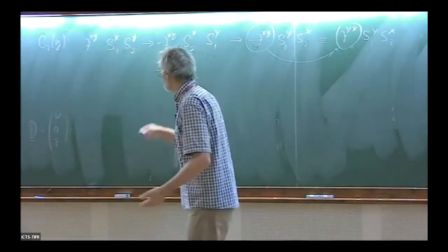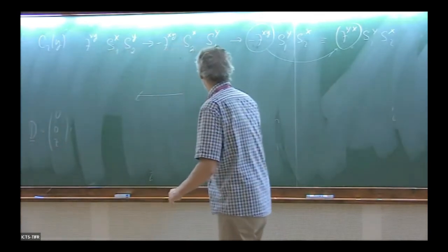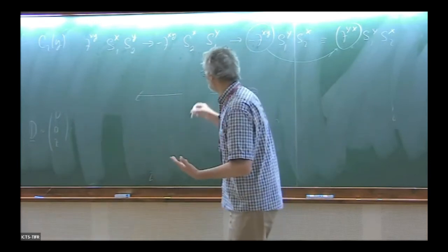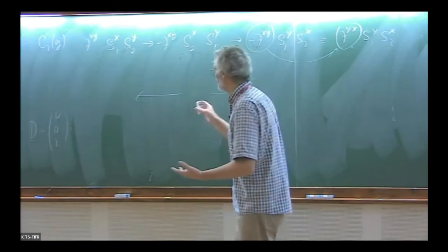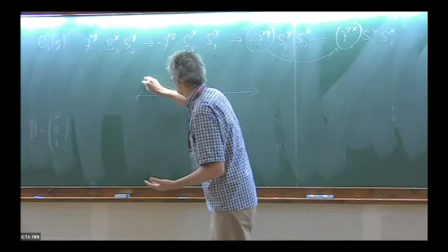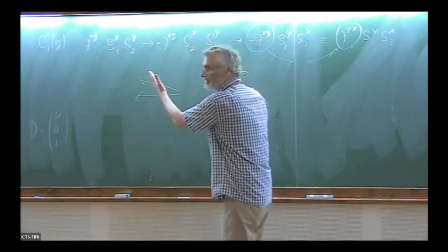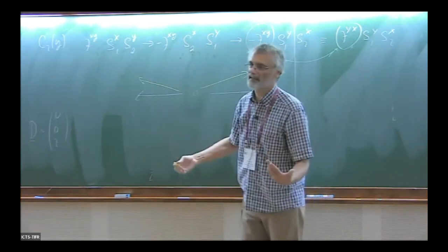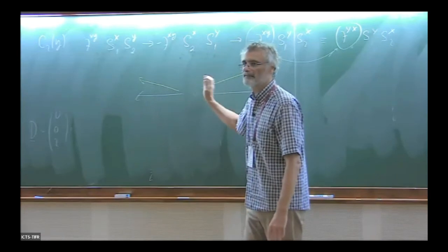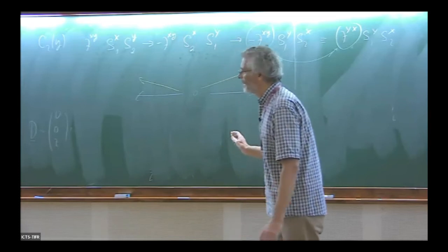So if we have a configuration, this typically arises next to an antiferromagnetic exchange. Antiferromagnetic exchange wants to make the spins antiparallel, and this term would like to have some finite volume. So suppose that the D vector is pointing out. It can gain volume if the spins start to tilt a little bit. If they tilt, then they will reach some compromise between the DM interaction and the Heisenberg exchange, and this type of magnetism will arise. It can give a small ferro component or whatever.